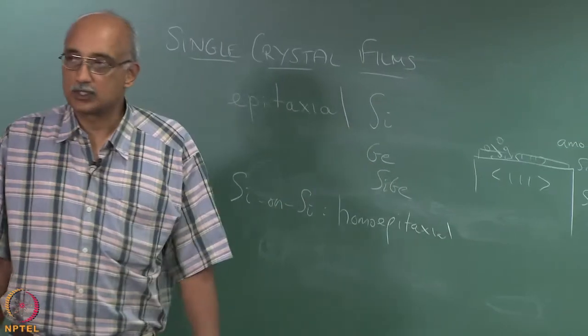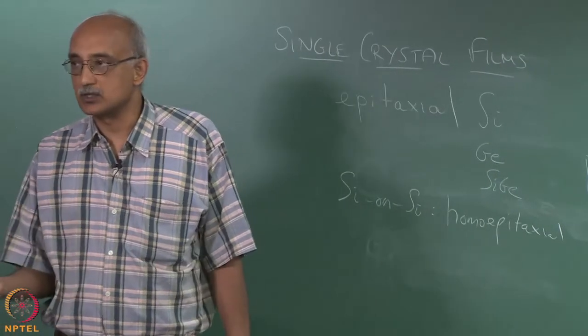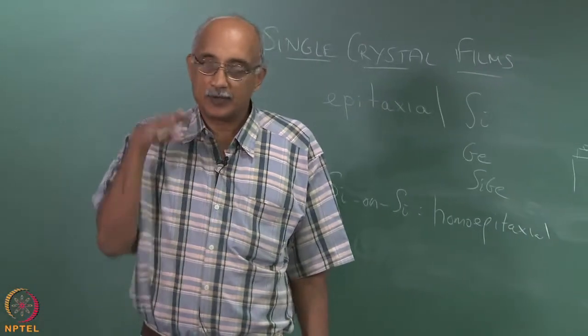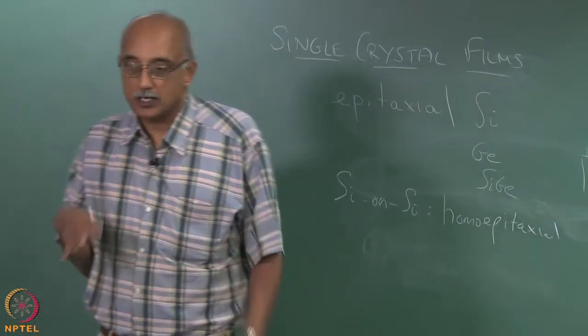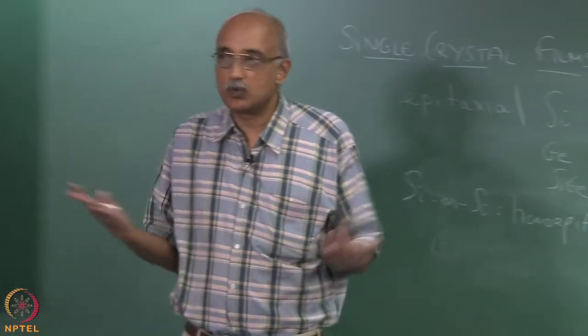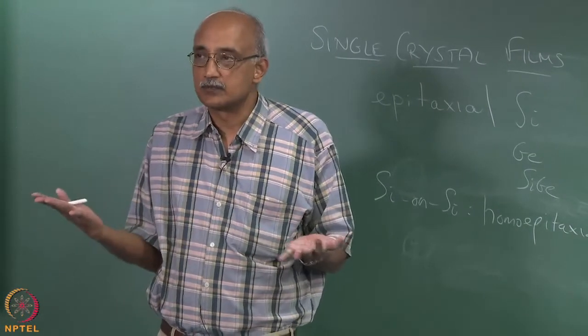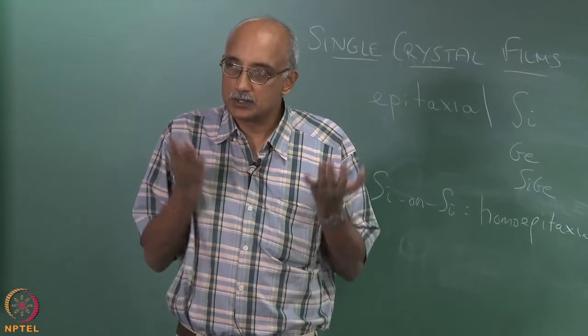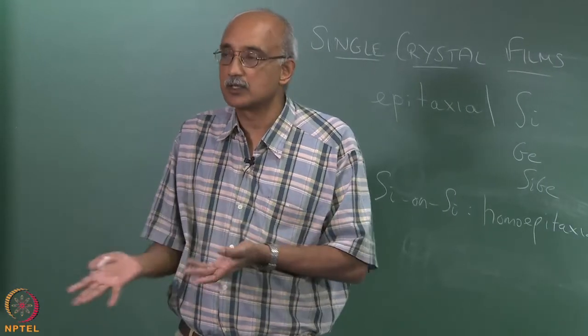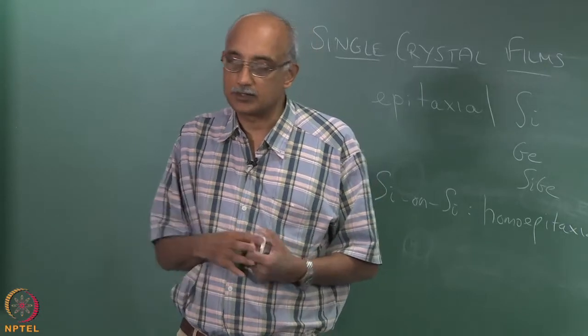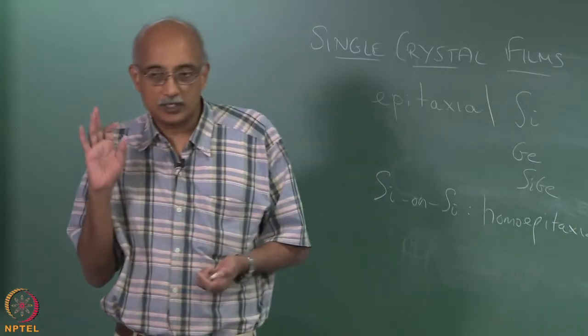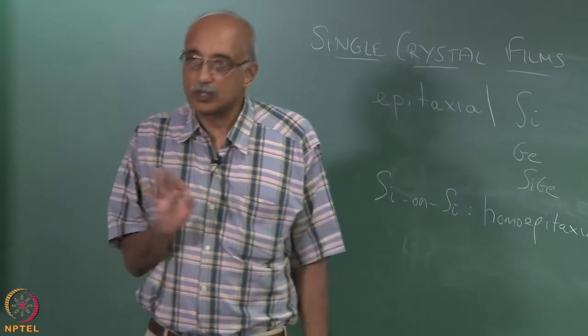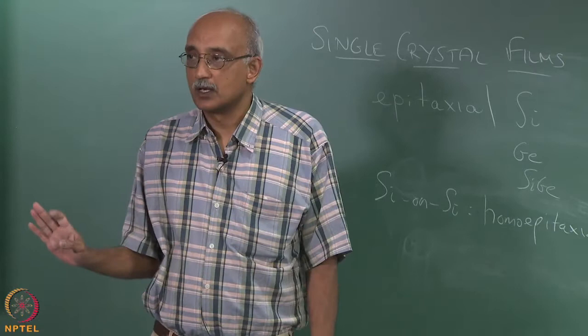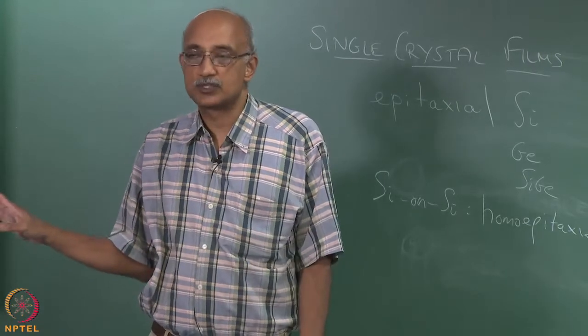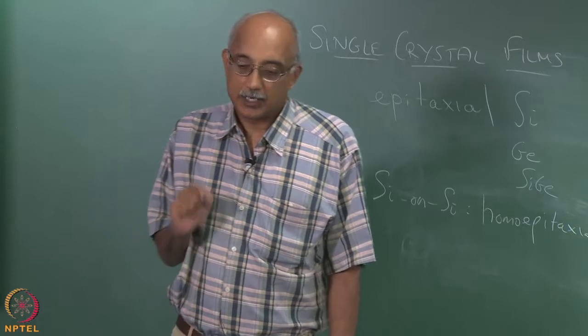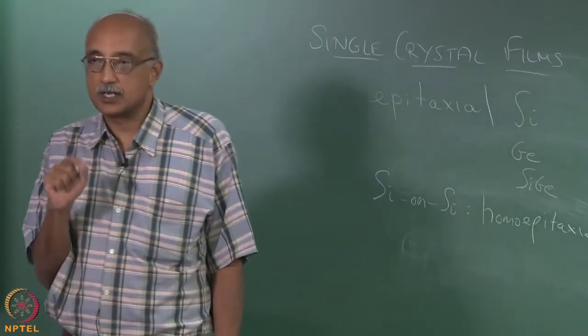The other reason why this could happen is if you have, again, impurities or contaminants on the surface. Here again, the vapor molecules that arrive at the substrate are not going to see crystalline silicon; they are going to see whatever contaminant is sitting on the surface. So, the molecules are going to orient themselves in accordance with the contaminant rather than in accordance with the basic underlying substrate material. So, the point is, if you are trying to make single crystal films, it is very important to have an oxide free surface, and it is very important to have an impurity free pristine surface. That is the only way that you can make a crystalline film happen.